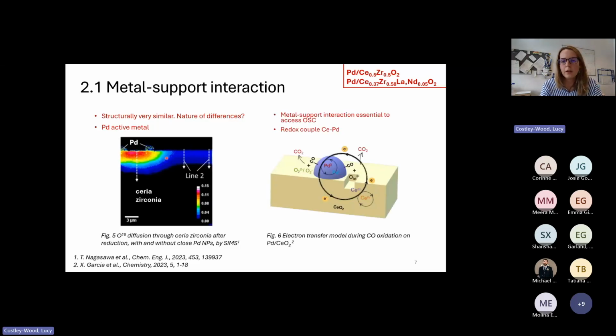The reason for this is because there is a redox couple at the interface between the cerium, which is cycling 3+, 4+, and the palladium, which is cycling metal and 2+. So when oxygen is removed, it diffuses from the bulk to the surface, and then it's released from the surface at the cerium-palladium interface via these redox mechanisms. And that's really crucial, and it really allows a lot more oxygen to be released once it's diffused to the surface. And once you remove more oxygen from the surface, you increase the concentration gradient, so you drive more oxygen to move from the bulk to the surface.